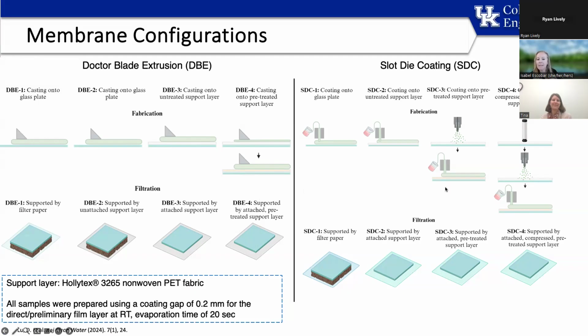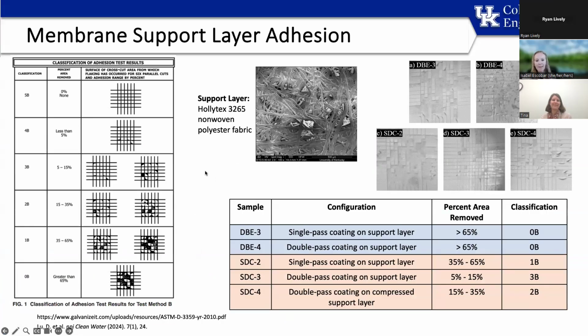that support. And similarly, at the slot die coating level, what we did was spray. So we added a dope spray on the support in order to do the same as that thin pass layer. And we also compressed it and then added that spray coating as a pre-treatment step. And we looked at how well those were attached to the membranes. So how well the support and the membrane were attached to each other. And we went to some ASTM methods in order to determine the classification of that attachment.